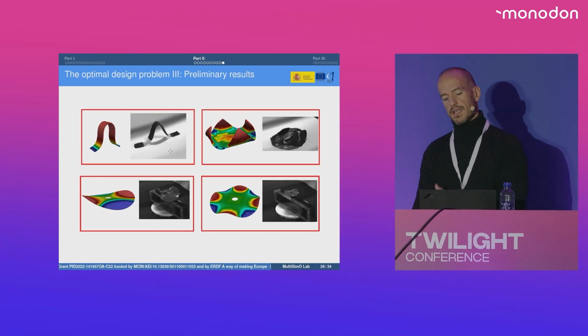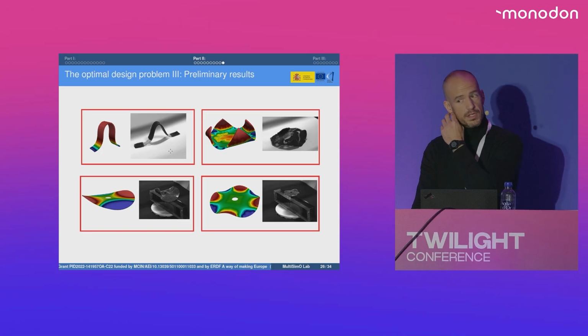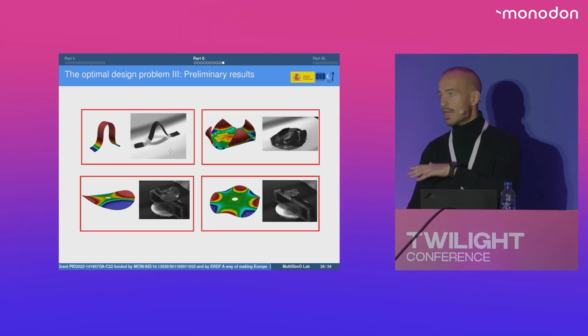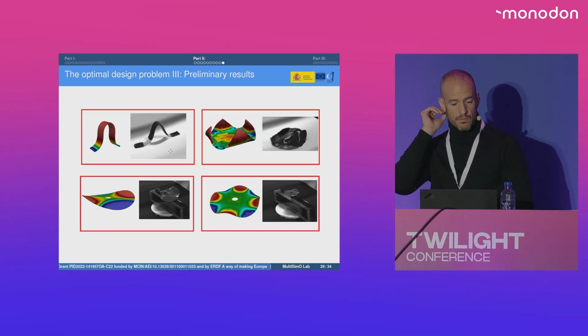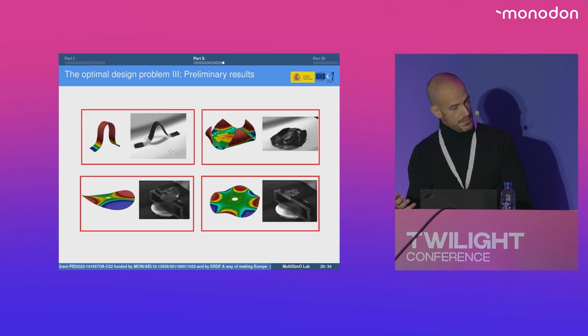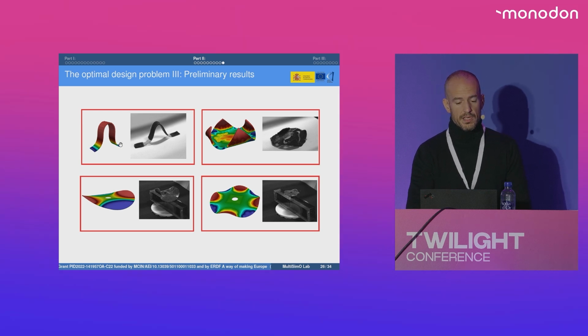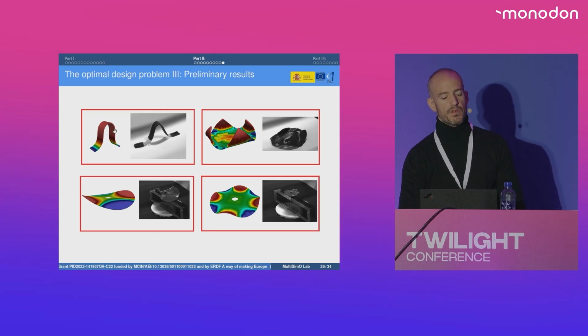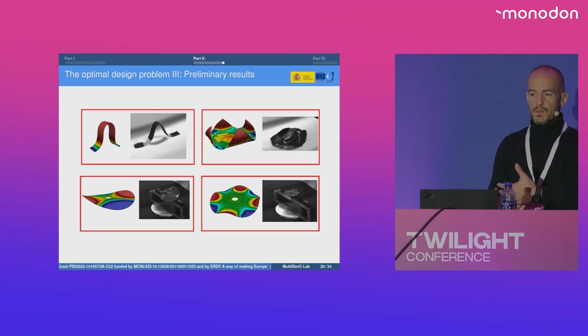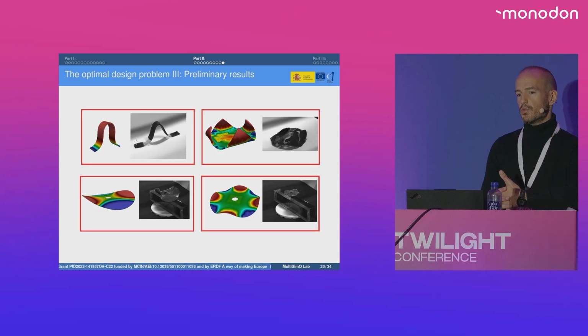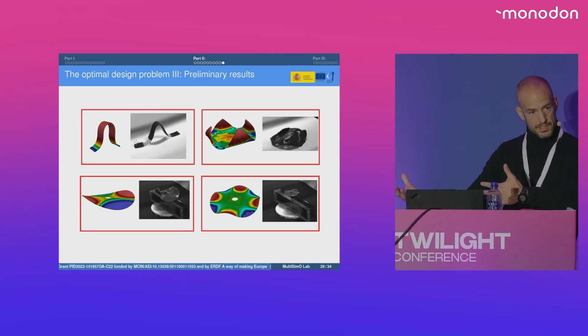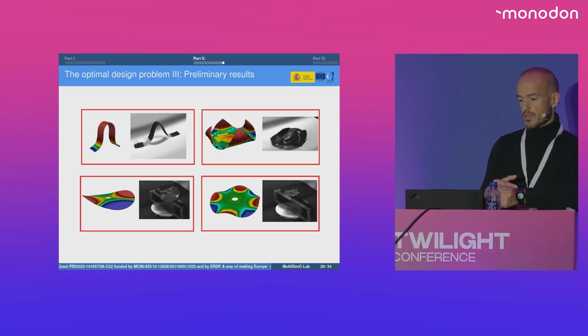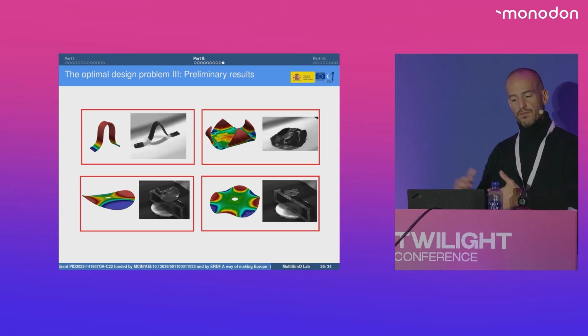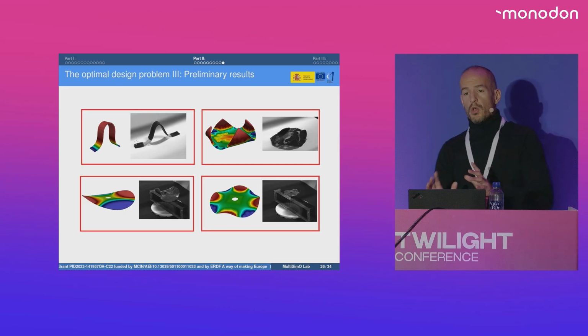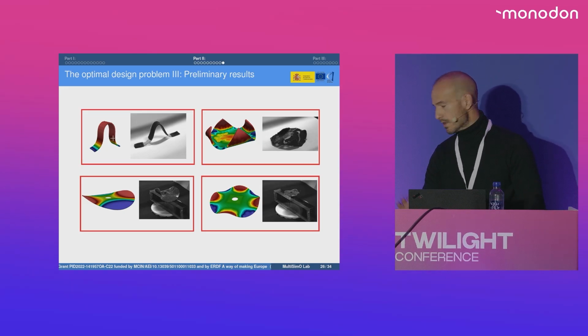Okay? And here are some preliminary examples that we obtained with our colleagues in Carlos III. All these designs were initially plain, okay? And then we said, okay, well, let's see what magnetization orientations we need to prescribe in order to attain a specific target configuration. We wanted to get this shape configuration. We run our topology optimization problem. We pass this information to our colleagues in the experimental lab. They magnetize according to the guides of the topology optimization algorithm, and then they again apply a magnetic field, and they get the magnetically induced deformation, which is pretty similar to the one that we are obtaining numerically. Okay?